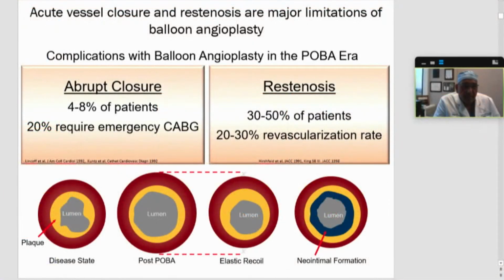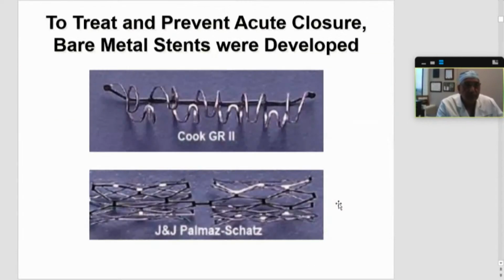So as you can imagine, after a balloon angioplasty, you have an improved lumen. However, there's an elastic recoil, which leads to early luminal loss, and then eventually there is a late luminal loss because of neointimal proliferation. So to treat and prevent acute closure, bare metal stents were developed.